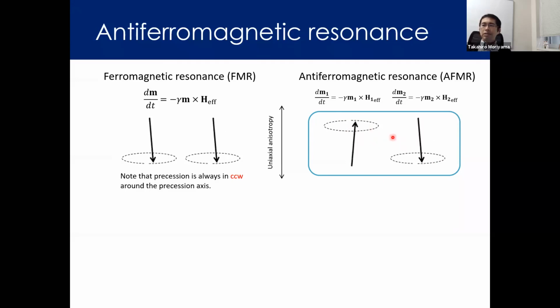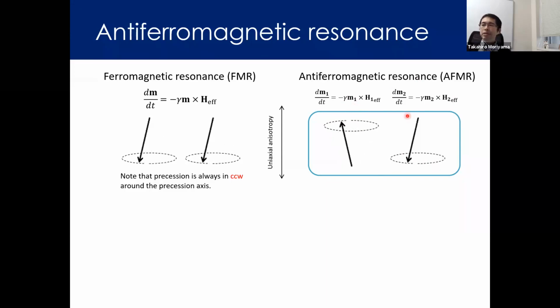So they still need to satisfy the equation of motion for each sublattice, as a precession motion will be like this way. Okay. So here you notice that in the ferromagnetic case, they can precess while keeping the moments parallel to each other. On the other hand, antiferromagnetic moments cannot keep the antiparallel coupling while precessing.